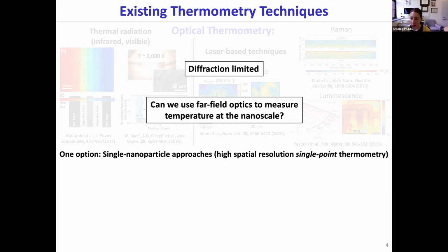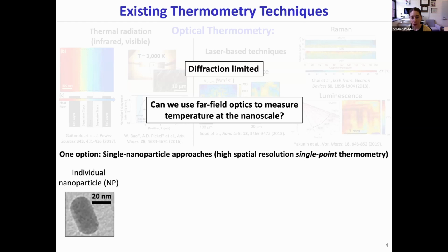One way to do that is to take advantage of the temperature-dependent luminescence emitted by a single nanoparticle. This approach only allows for measurements at a single spatial point, and that's an important limitation that I'll come back to. But for situations where we need to know the temperature at a single critical location, then this approach works very well. The idea is that we take a single nanoparticle and we place it at the exact location on a sample where we want to measure temperature.